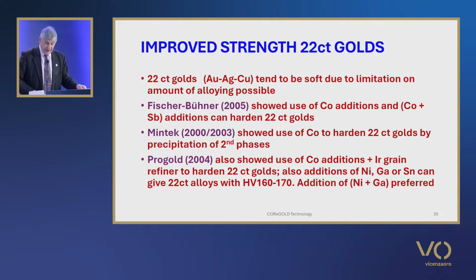I'm now going to move on and talk about improved strength 22-karat gold alloys. As noted in my presentation last year here at JTF on the benefit of titanium alloying additions to precious metals, 22-karat golds also tend to be soft due to the limited amount of alloying element that can be added, which is typically silver and copper. Fischer-Bühner developed 22-karat gold alloys containing cobalt or a mixture of cobalt and antimony, as I mentioned earlier, to harden 22-karat golds by conventional alloying. And these have increased hardness by age-hardening treatments, as discussed earlier.